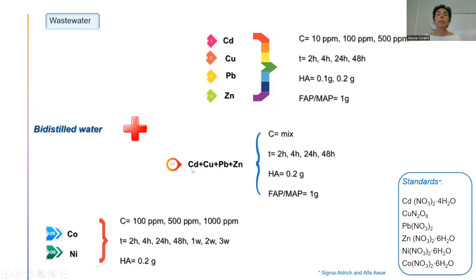And then we mixed all the four metals in the supernatant with the same concentration, with times from 2 hours to 48 hours.